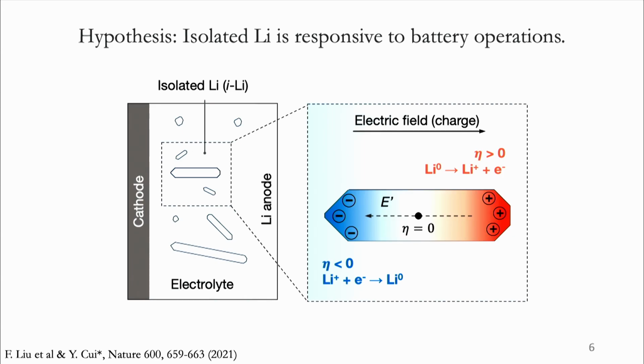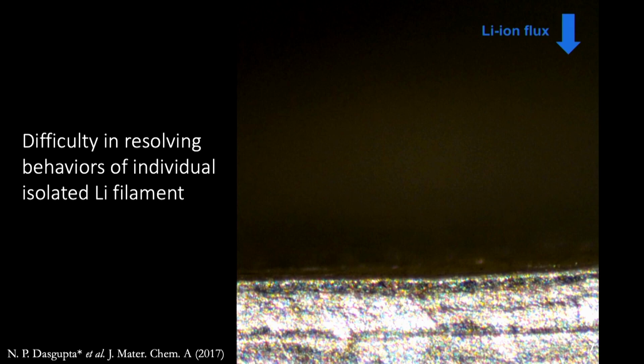electrolyte. So the net outcome of this asymmetric deposition and dissolution is a spatial dislocation of this filament toward one of the electrodes. For example, for the case we're seeing here during the charging process, it moves toward the cathode side. And during the reverse process, during discharging, it moves toward the anode side. So this is based on hypothesis.